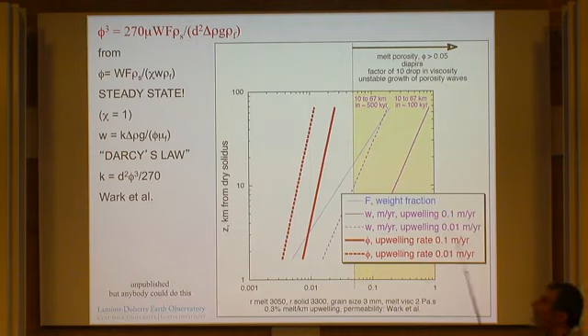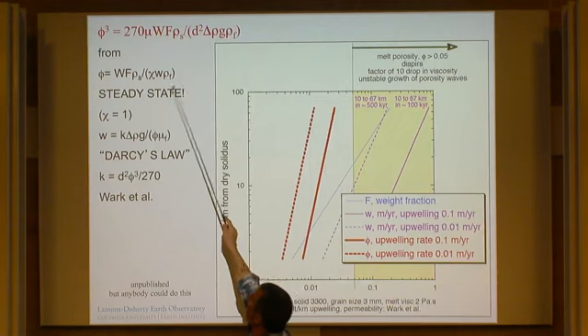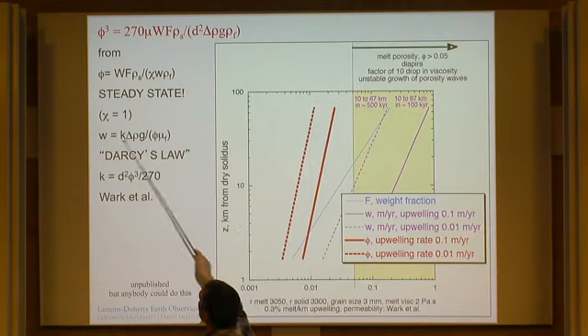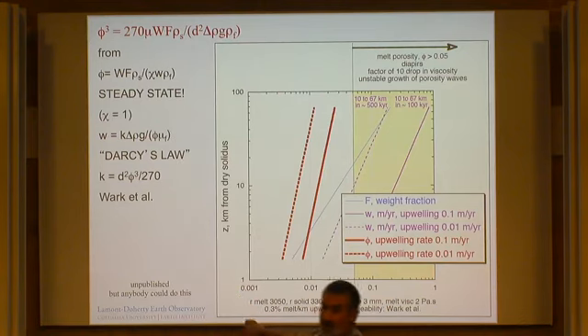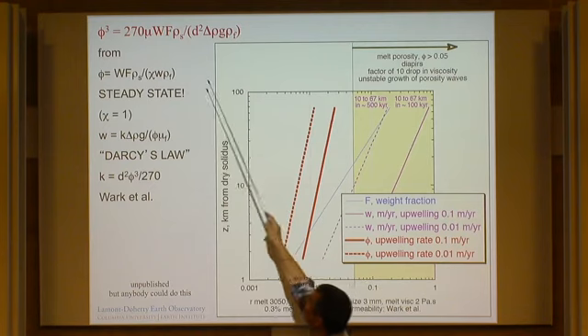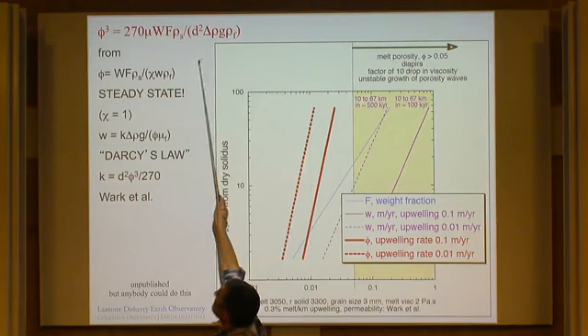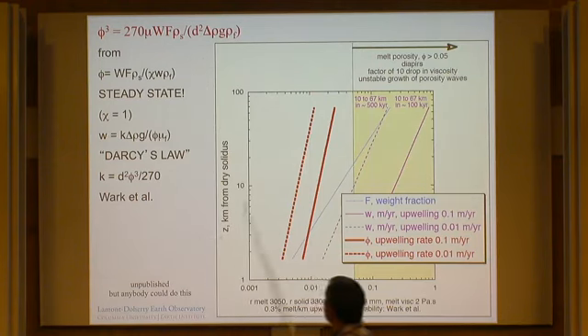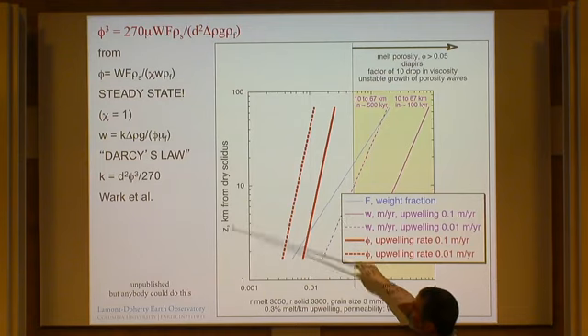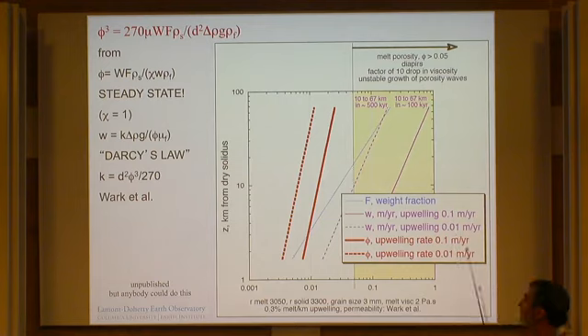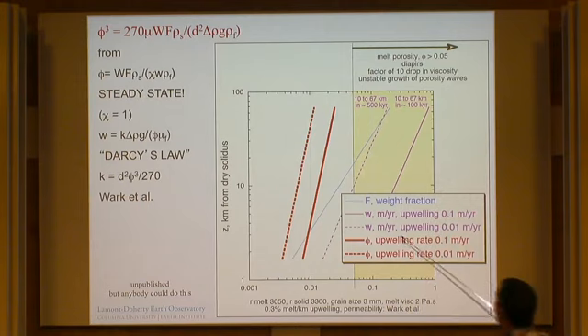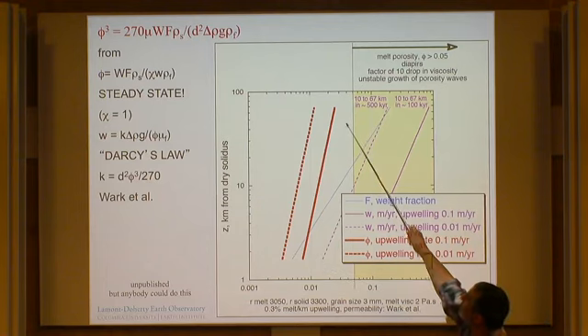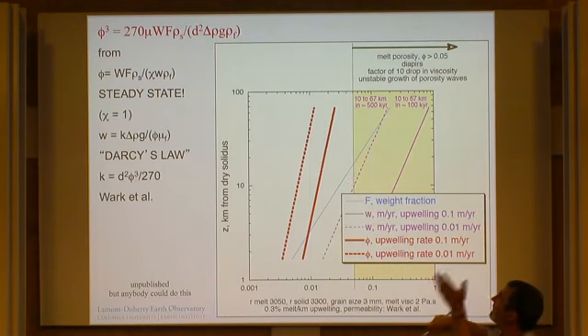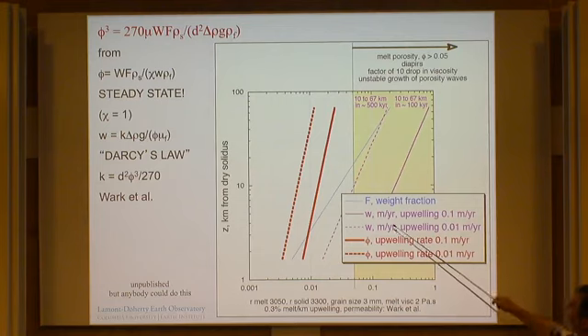Okay, so the nice thing about this is that then we can simultaneously solve this steady state approximation and Darcy's law, given this permeability law, and we can solve for the porosity as a function of the upwelling velocity, the melt fraction and grain size, for example. And so you can make this sort of composite diagram where we're looking at height in the decompressing mantle underneath a mid-ocean ridge. And for example, we can say that the porosity for a fast-spreading ridge might get up to 2 or 3% at the top, and at a slow-spreading ridge, a smaller value, because basically the draining rate is pretty high.